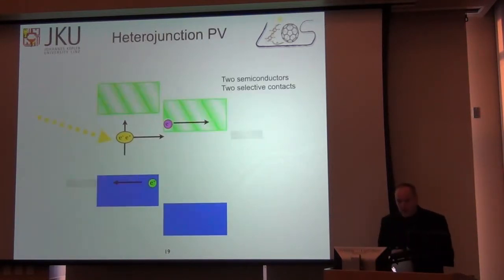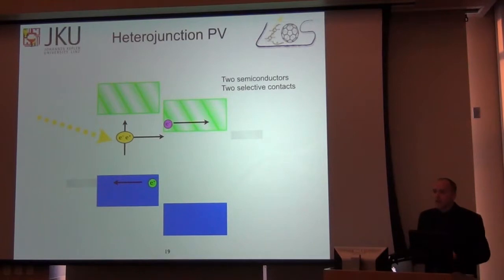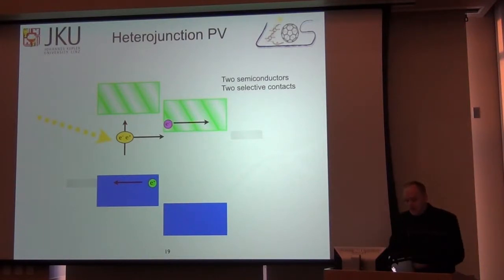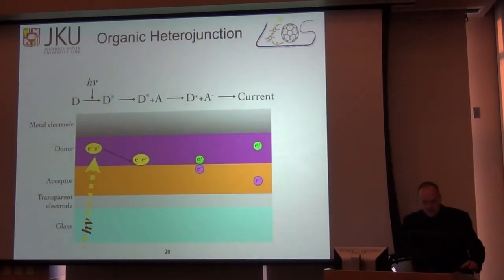And so this is the heterojunction, the photoinduced charge transfer that I described earlier with the fullerenes. So you create an exciton, you dissociate the exciton at the interface, and you harvest the electron and the hole, but now no longer at the optical band gap, but at the transport band gap, so the effective band gap. This energy loss is very significant. I'll get back to that in a minute.